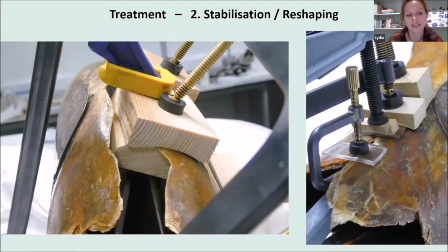Further on, the plain sides of the blocks allowed me to apply clamps without them sliding off the curved surface of the horn. I left the clamps in place overnight to ensure the horn material has fully dried and regained its sturdiness. Unfortunately, it is not possible to reduce or remove such severe distortions as given on this object in one go. I had to repeat this process between 5 to 10 times per area, which made this conservation step the most time-consuming.